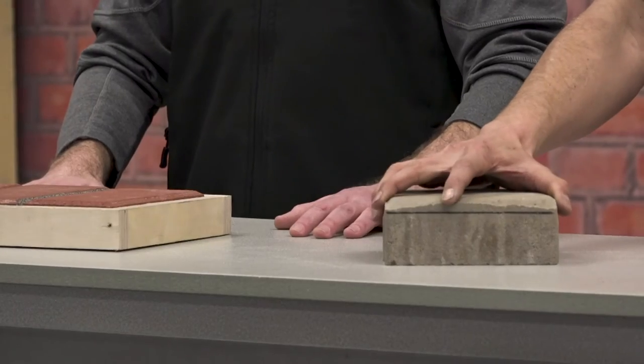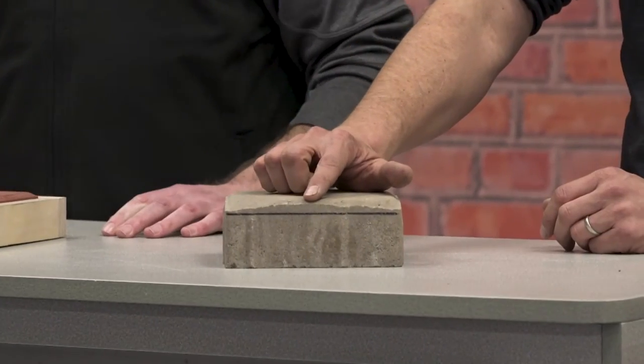Yeah, and in due time, I would assume if we're pounding that with water, because with our polymeric sands, it's a much more common practice to see somebody has underwatered a joint and had an issue with it than has overwatered the joint. Am I right, Mike? Yes. I'd say if there's 10 jobs out there, 5 of them are watered correctly. Yep. And probably the other 5 are underwatered. Right. So this is kind of making it easier, because when you put water on there and it's sitting in that channel, the physics of it is it's going to continue to drain. And in theory, or in reality, it's going to give you a much thicker crust in that joint. Right. So if you take a look at our close-up here of this paver, that's a line showing the proper joint height.